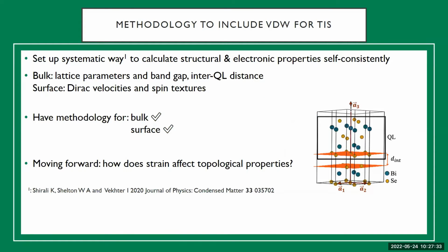So we now have a methodology to calculate the structural and the electronic properties. And we were able to obtain the properties of the bulk, such as the lattice parameters and the band gap, and properties of the surface, such as the Dirac velocity and the spin texture, properly. So moving forward, we next asked the question of how strain affected the topological properties in these materials.